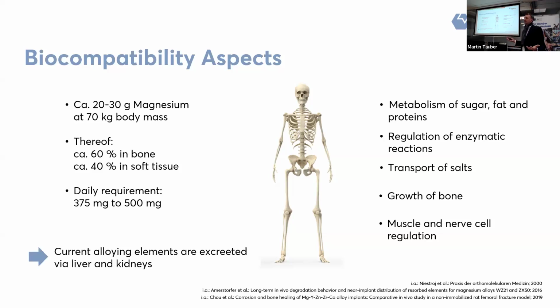They are stored mostly in bone, exactly where the implants are implanted. And we anyways have a daily requirement of up to 500 milligrams of magnesium. Just as a reference, one of the screws in an average size has around 150 milligrams. So it wouldn't be an issue if one screw would dissolve in a day, because with that, you would just cover a third of the required amount of magnesium.